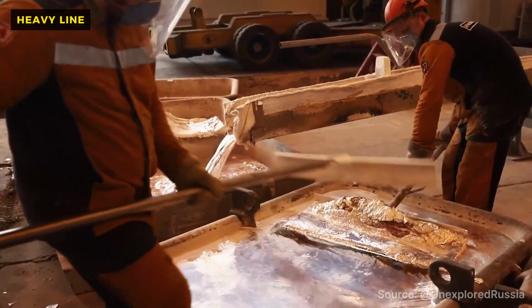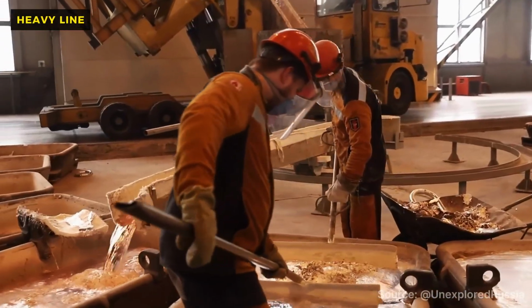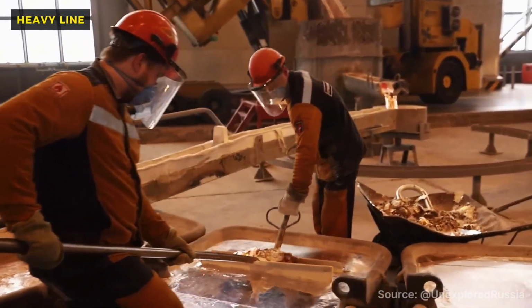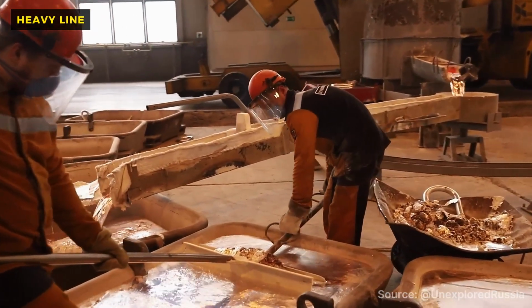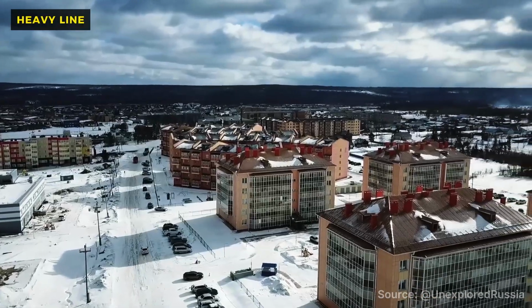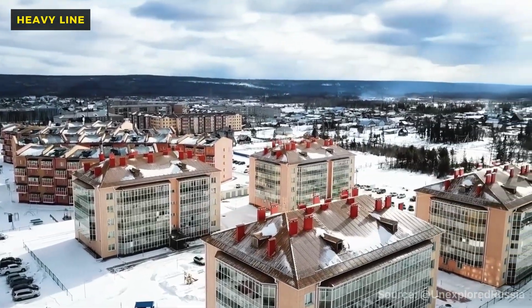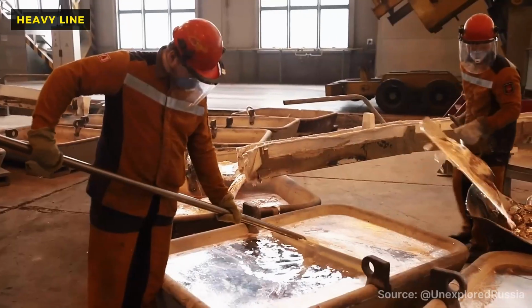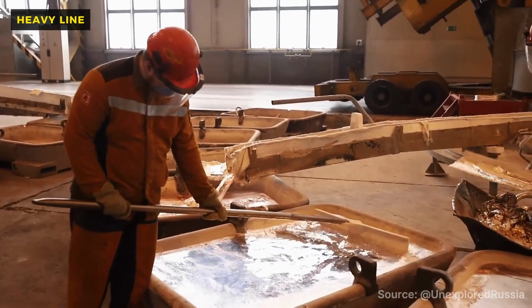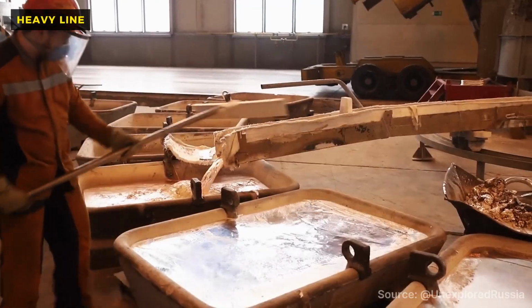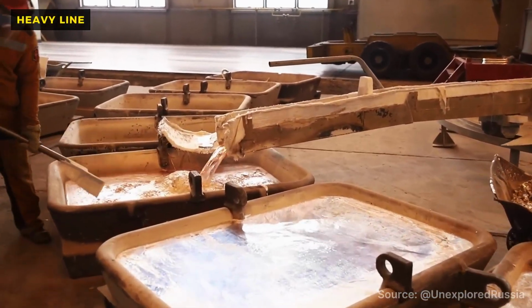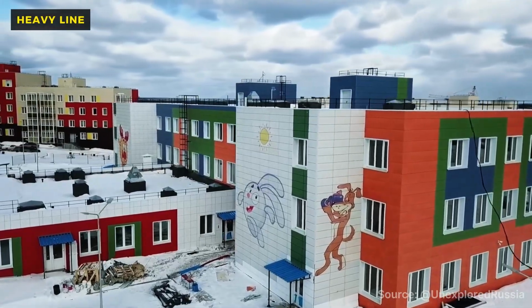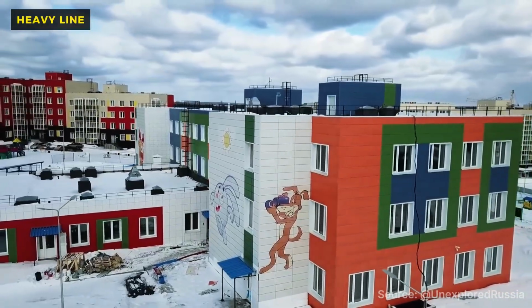The sheer violence of this chemical reaction is hidden beneath a deceptively calm surface, a crust of solidified chemicals that traps the heat and gases inside the pot. Underneath this crust, the oxygen ions migrate to the carbon anode and react with it, essentially burning the carbon to produce carbon dioxide, which bubbles away while the aluminum ions drift downward, pooling as a layer of molten metal at the bottom of the crucible.